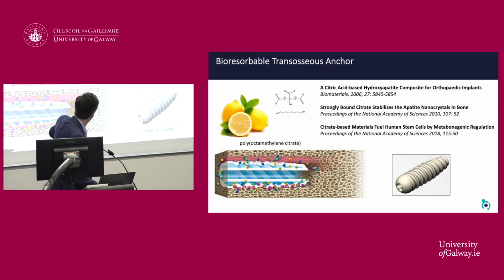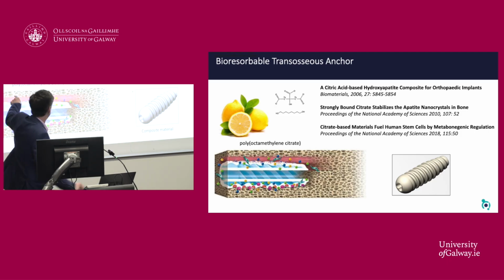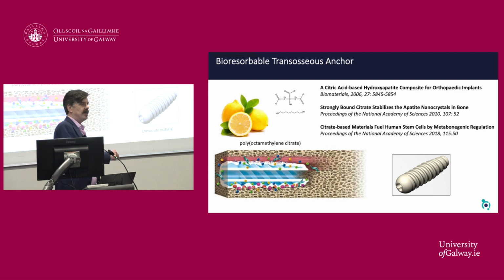What's nice about this material is that, well, a couple of things. One, it resorbs over months and years, so it will slowly degrade and it will slowly be fully resorbed. The other thing is that citrate is really important in bone metabolism. Citrate is important in bone growth. So the fact that we have made our device out of citrate is a really nice approach.